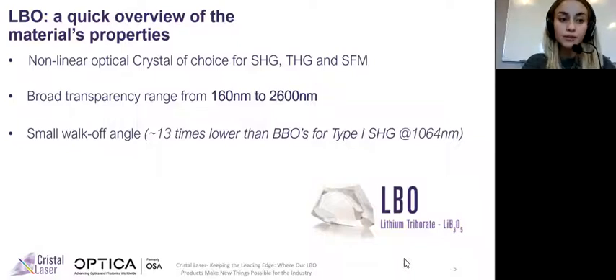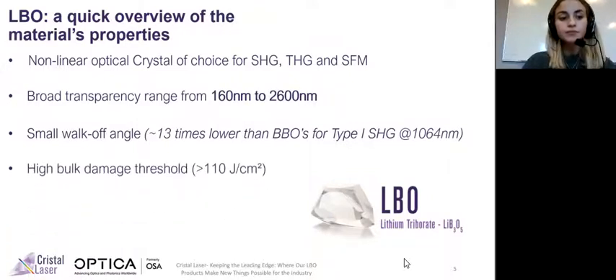LBO also benefits from a small walk-off angle, which is 13 times lower than BBO, BBO being another type of nonlinear crystal, for type 1 SHG at 1,064 nanometers. LBO also has exceptional power handling properties thanks to its high bulk damage threshold, which is over 110 joules per square centimeter for wavelengths of 1064 nanometers and for a nanosecond pulse.